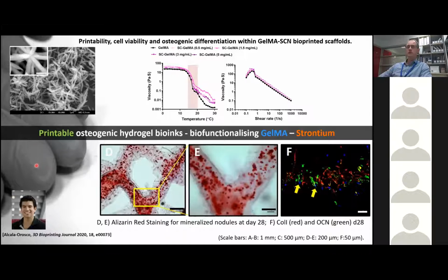First of all, in terms of development of an osteogenic bioink, one way to provide cell instructive capability is to include different differentiation cues, in this case in the form of strontium in a nanoparticle formulation. If we're going to look at additives within our bioinks, first of all, we want additives which can modulate the printability, so rheology modifying capabilities. The inclusion of different nanoparticles within a hydrogel can provide modifications to the viscosity profile. In this case, with a range of different concentrations of strontium nanorods we were able to synthesize, we incorporated those into a GelMA strontium bioink.